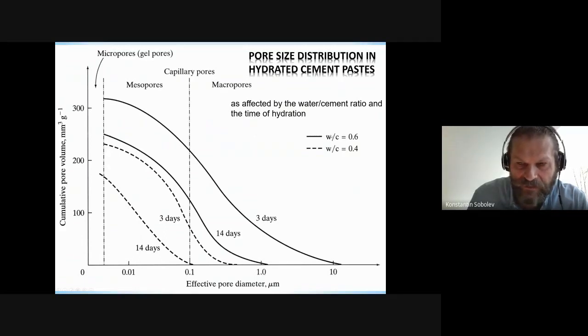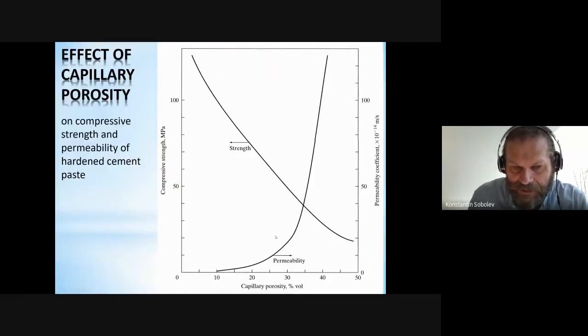So if we think about water to cement ratio to be a key parameter, obviously if you have water to cement ratio less than 0.5, it will result in better compressive strength, but what is more important, in lower permeability. So lower capillary porosity and lower permeability. And this is our target.